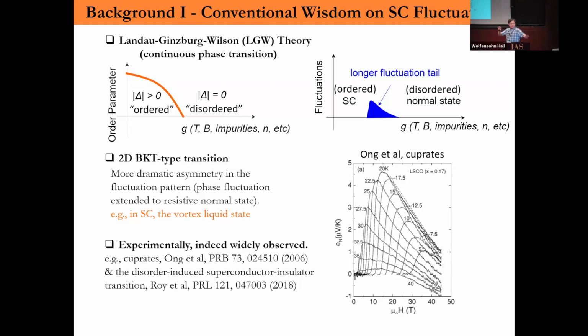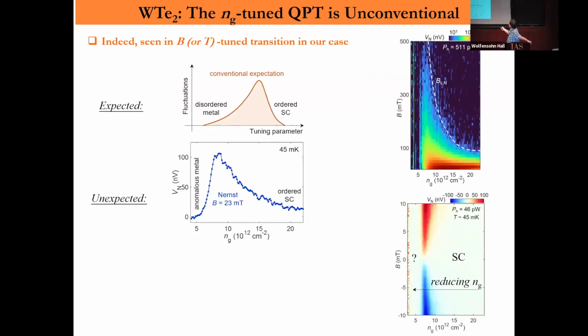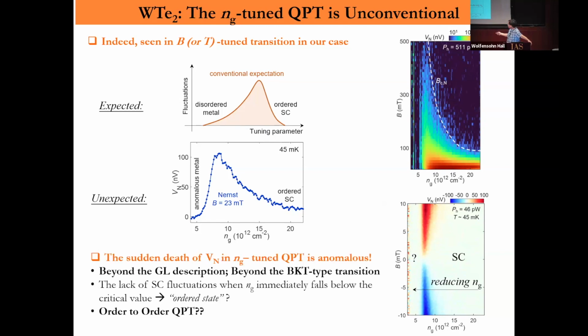There's an asymmetric pattern, right? Deeper, larger fluctuation on the normal side, not on the superconducting side. And we observe here it's very different - it's too sharp a transition here. So the transition suddenly disappears here, sharper than even the superconducting side. If you look here, the superconducting side is also sharp because it's ordered, but it's even sharper on the normal side. That's something we really don't understand.